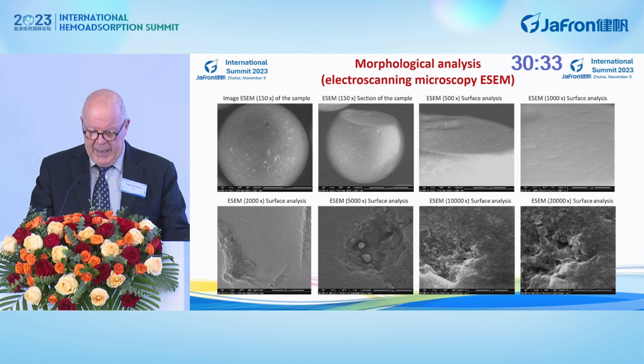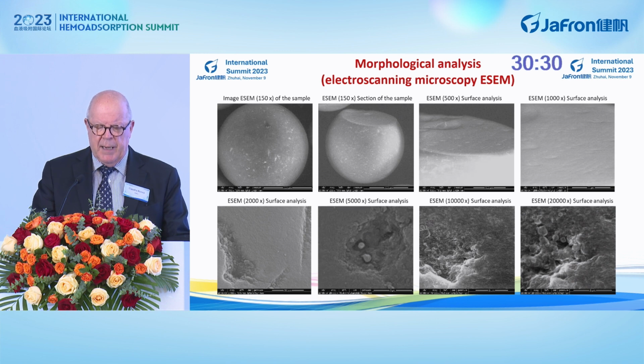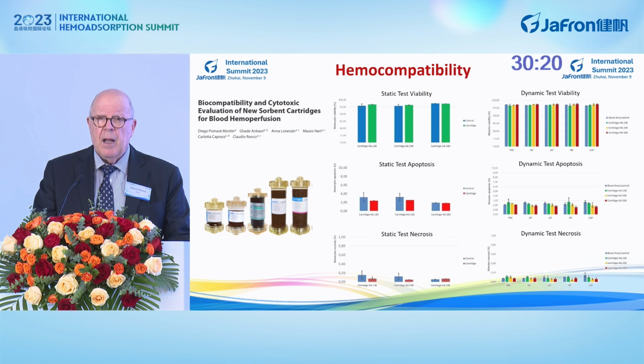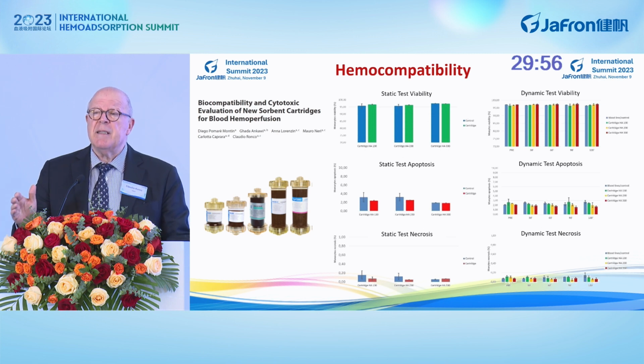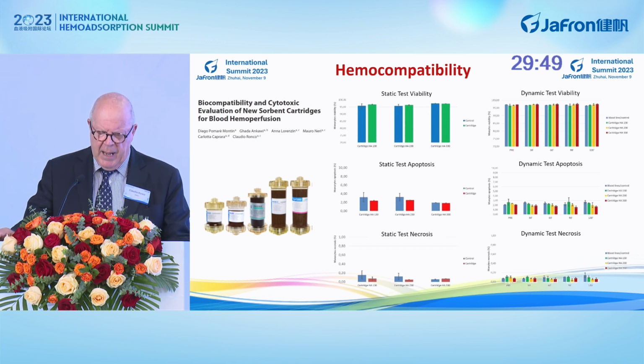There is a possibility to analyze by microscopy, especially with electroscanning techniques, not only the surface of the sorbent, but also the internal structure and the nature of the different pores. Of course, all the effort should be made to generate a sorbent which is biocompatible. And we have tested in our laboratory the biocompatibility, or even better, the hemocompatibility of the sorbent materials included in these cartridges that you see. And both in static and dynamic tests, we could not find any difference in terms of viability, apoptosis, or necrosis of the cells incubated with the biomaterial.